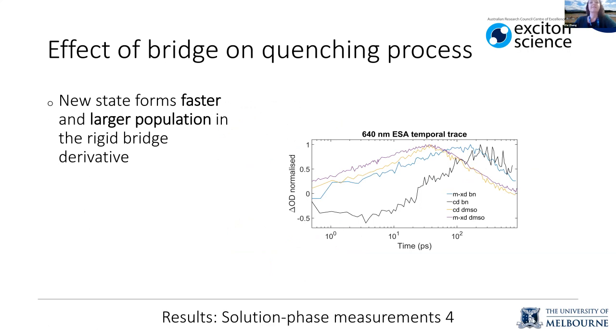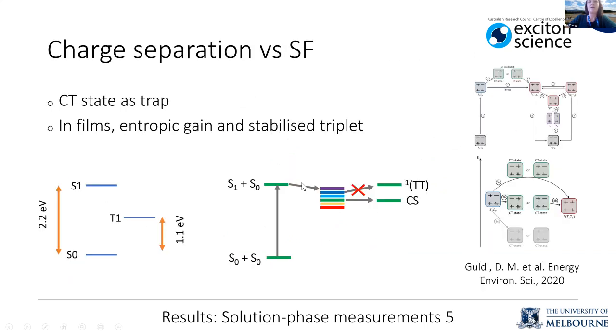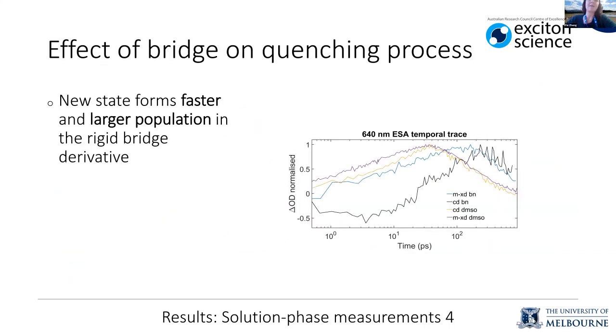I could also see that the bridge has an effect on this quenching process. So you can see that the rigid dimer forms fastest, and forms fastest in the most polar solvent, whereas that more flexible linked dimer in the black forms slower, and slowest in the lowest dielectric solvent. So the bridge is definitely having an effect on this charge transfer process.